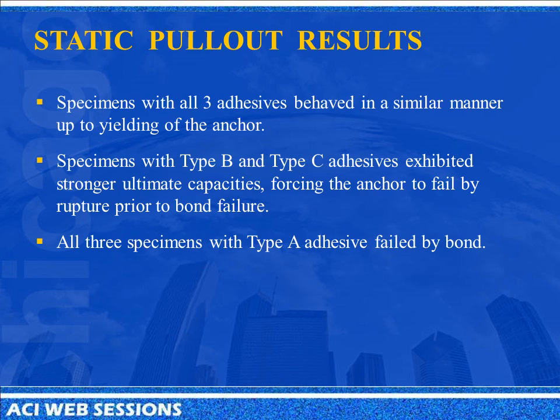I'm going to show a little bit of the results that we got during the testing. So I'm going to start off with the static pullout tests. All three adhesives behave in similar manner up to yielding of the anchor. Generally speaking, the specimens with type B and C, which are the epoxy-based adhesives, exhibit a stronger ultimate capacity, forcing the anchor to fail by rupture. Whereas specimens with type A, which is acrylic-based, failed by bond.